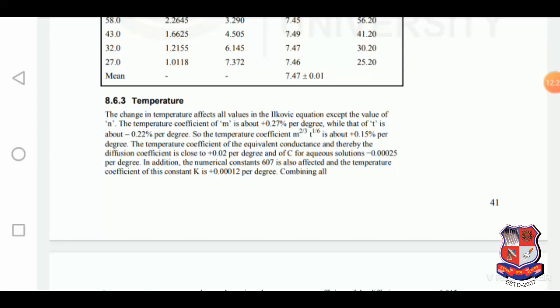Temperature. The change in temperature affects all values in the Ilkovic equation except the value of n. The temperature coefficient of m is about plus 0.27% per degree, while that of t is about minus 0.22% per degree. So the temperature coefficient of m raised to 2 by 3, t raised to 1 by 6 is about plus 0.15% per degree. The temperature coefficient of the equivalent conductance, and thereby the diffusion coefficient, is close to plus 0.02% per degree, and of capital C for aqueous solution is minus 0.00025 per degree.